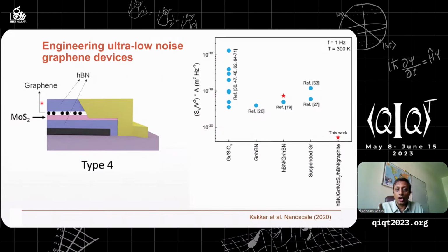But that's not all. Contacting strategies is one of the important aspects that many people leave out. Contact resistance is one of the big problems in electronics, but the contact noise is something which many people often undermine very badly and, I think, very incorrectly. And that needs to be understood. For silicon, gallium arsenide, and these kinds of materials, the contacting strategies have been developed over the years and they're very well known. But in the case of graphene and other two-dimensional material-based quantum devices, for example, if you want to make a qubit on bilayer graphene, you've got to do something about making contacts which are very low noise in nature.